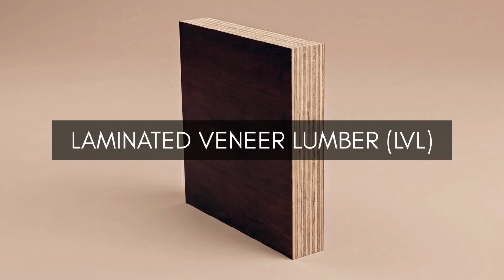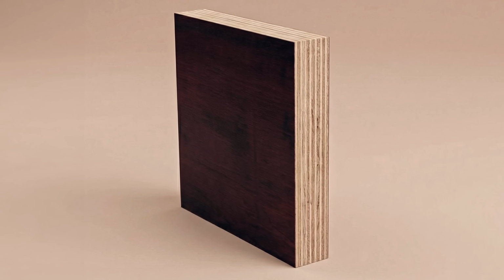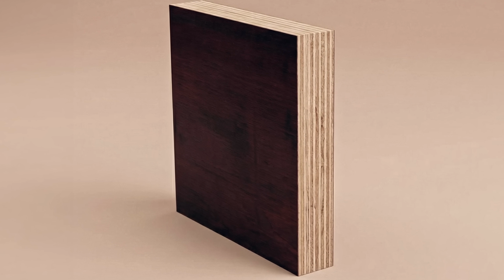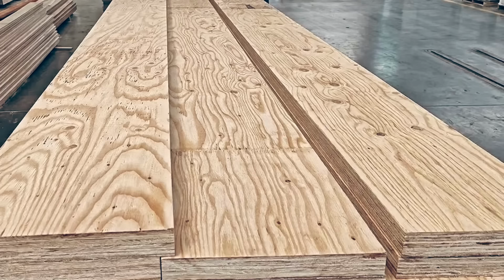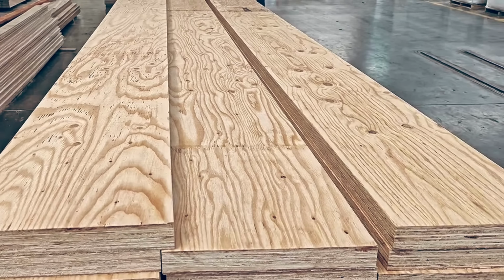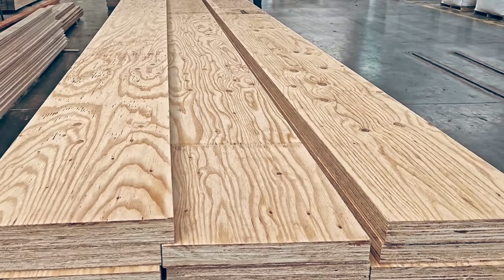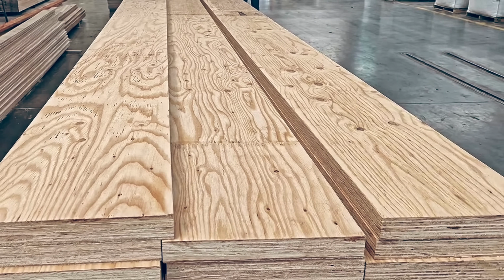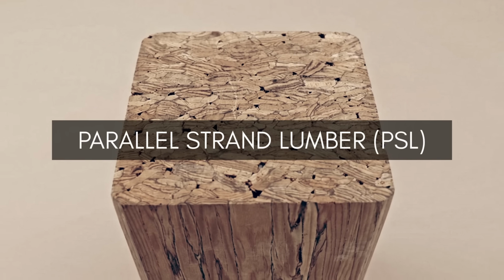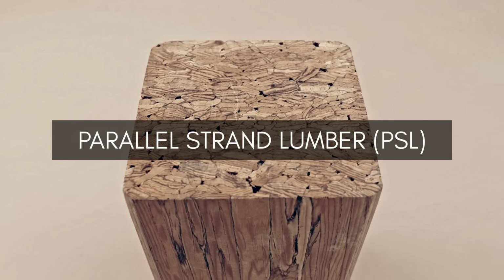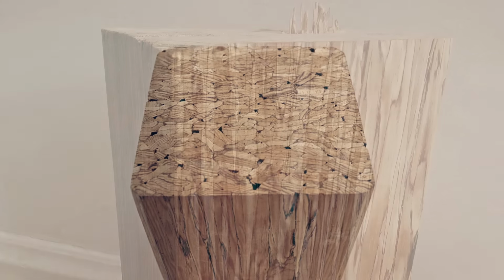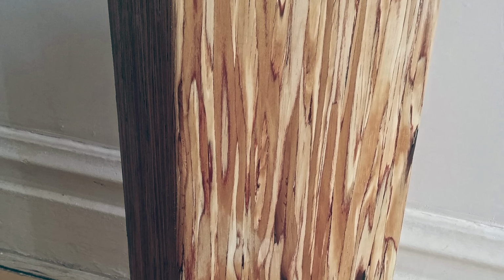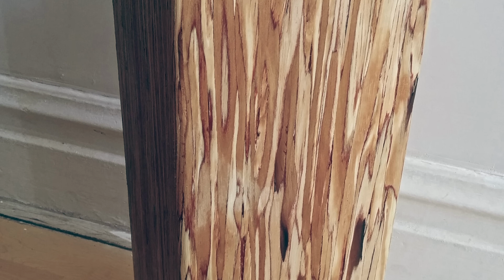Laminated veneer lumber, or LVL, is created from thin veneers layered with parallel grain. Depending on the grade of lumber it replaces, LVL allowable bending stress values can run roughly 1.5 to 2 times those of standard dimensional lumber. Parallel strand lumber, or PSL, is made from long, clipped veneers at roughly a 300:1 length to thickness ratio, providing the high strength needed for heavy-duty columns and headers.